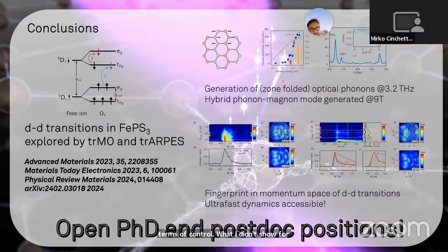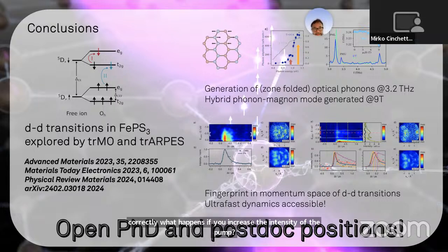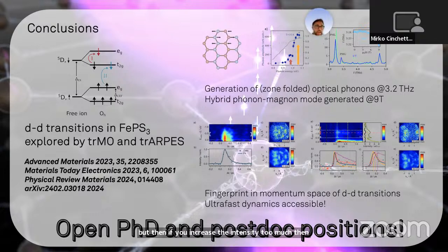What I didn't show, for example, is that you can also change the amplitude of the phonons by changing the polarization of the pump, this kind of optical control, if you want, of this kind of modes. Then, of course, what you mentioned is mainly what happens, if I understood correctly, if you increase the intensity of the pump. There we didn't do experiments yet, but this is something that can for sure be done. For example, it is known that in other 2D materials you can go in a range where you have excitons, but if you increase the intensity too much, then the excitons start to interact with each other, and they decay into single particles. So this probably can also be applied to this kind of DD transitions.